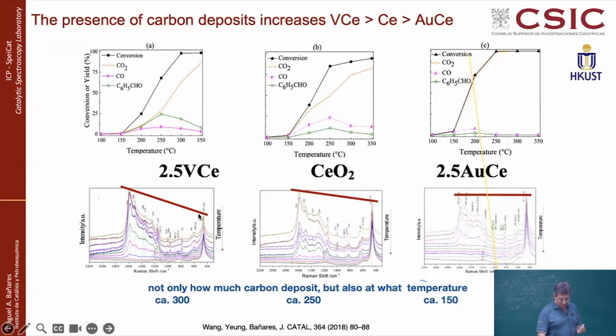You can look at the Raman bands and normalize to the intensity of ceria, which can be used like an internal standard. Then the spectra are vertically offset to see the details. This is giving a very qualitative image about the amount of carbon deposit molecules that accumulate at the surface of the catalyst during reaction. In a very qualitative manner, you can see that there are more carbon deposits on vanadium ceria than on ceria than on gold ceria.